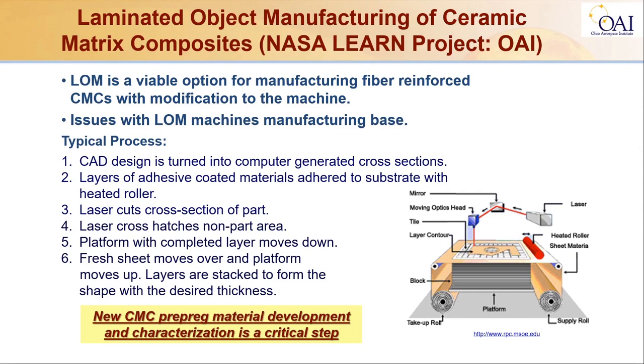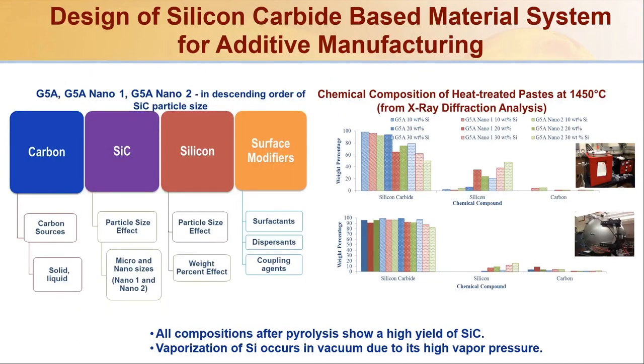So as many of you know, since these fibers are very expensive, and this machine, even though there are some available with some universities and some other places, is extremely expensive to use with a large volume of fibers. So what we tried to do is develop different technology and see how we can really integrate it. So in this case, the development of new CMC prepreg material became a really critical step. This slide shows how we tried to come up with a compositional design of prepreg material, which can yield a high amount of silicon carbide, which is needed for the additive manufacturing.